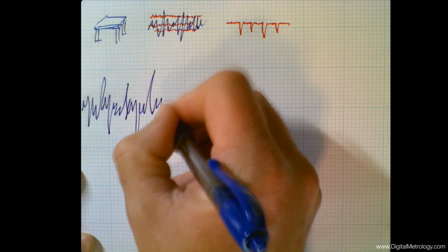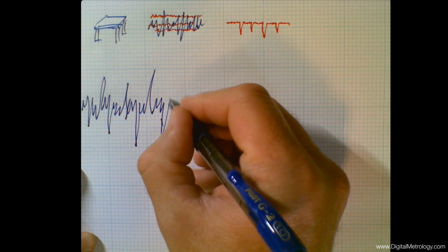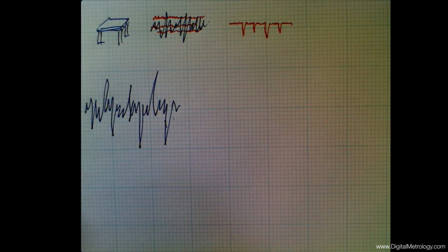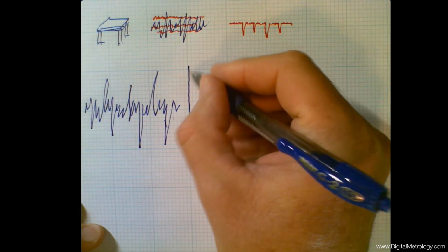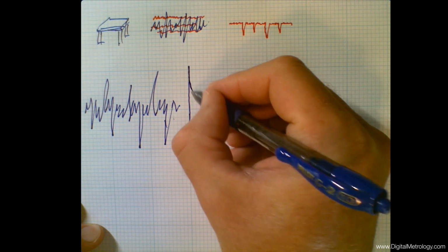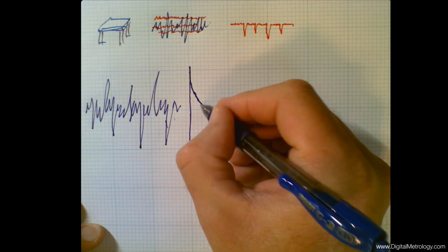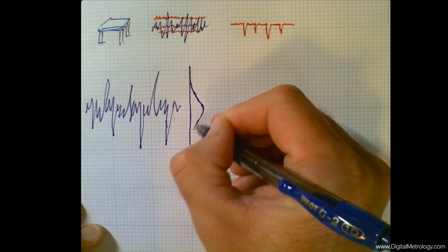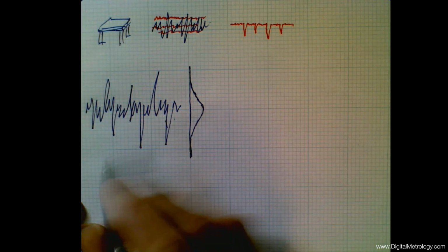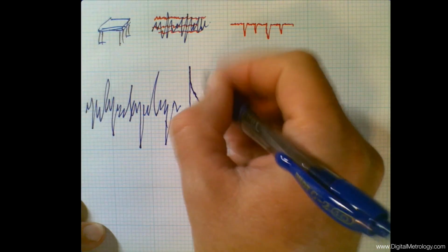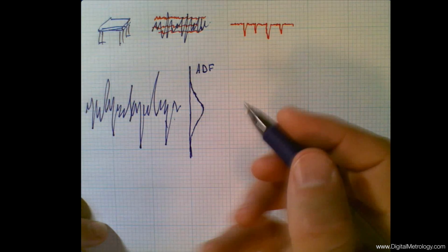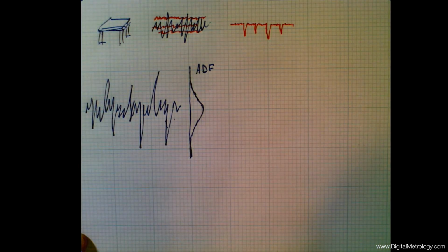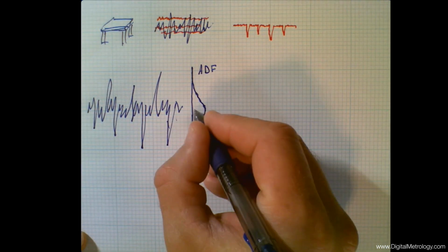our plateaued surface. Let's look at the rough surface, like the wood of the table before we started sanding it. And let's look at this a little bit through the eyes of maybe mathematics. This surface has a distribution of heights. There's kind of a bell-shaped curve that represents where the points are. There are more points in the middle and fewer points out at the edges. This curve we call the amplitude distribution function in surfaces, but it's kind of a histogram. It tells us where things happen. And there's a lot happening around the middle of this surface.